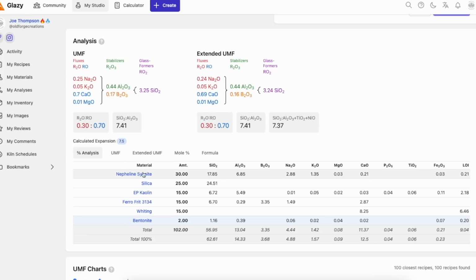So there is this complexity to each ingredient where it is very difficult to just look at the ingredients and see the underlying chemistry unless you have them all programmed into a UMF calculator, which not only takes them apart so that you can see what proportion of each category is within an ingredient, it also uses the molecular weight of them, where larger elements you get fewer of them per mass. A kilo of one ingredient doesn't necessarily mean it's got the same number of particles as a kilo of another ingredient, so you have to take that into account as well.